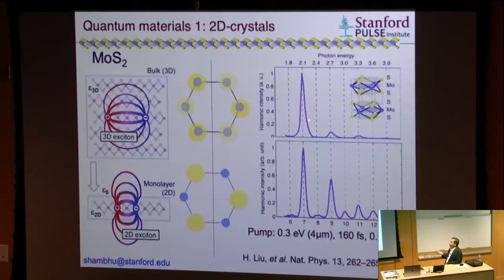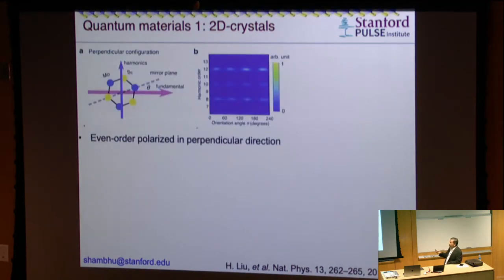This is the harmonic spectrum, a portion of the spectrum that we observed from 3-dimensional MoS2. This is the spectrum from single-layer MoS2, and sure enough, you see the additional even-order harmonics that we just talked about, in the case of this broken inversion symmetric system. So this was an interesting observation, but there was something more to it that drew our attention quickly, which was this.